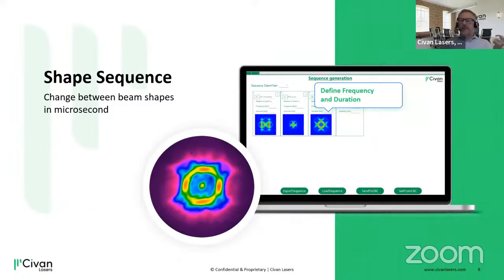Humping is a periodic syndrome, so you want to disturb the periodicity of it. And hot cracking is typically an issue of thermal gradients. So you would use a flat thermal profile across the weld section in order to avoid cracks. And switching with megahertz, we are able to basically apply all strategies at once.